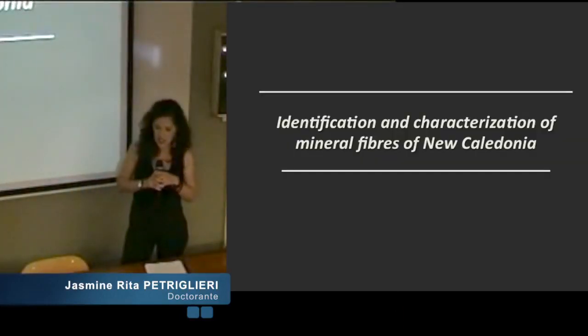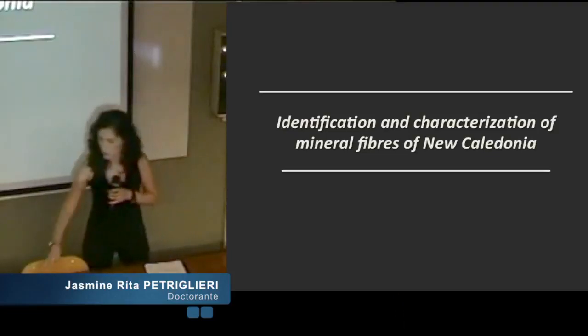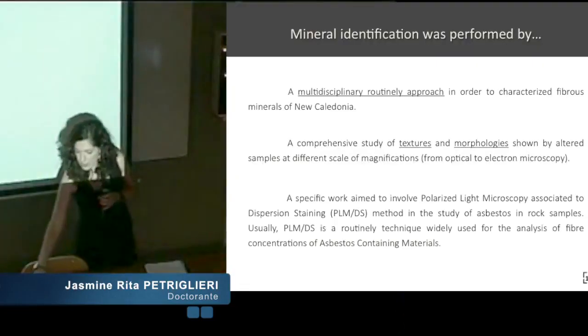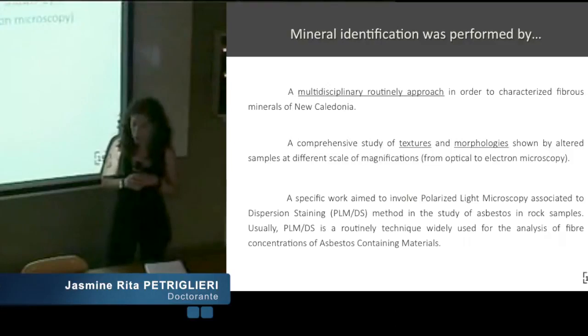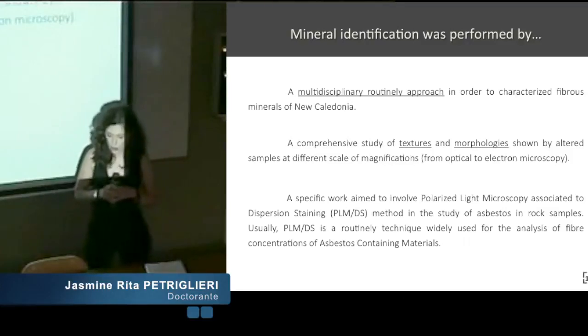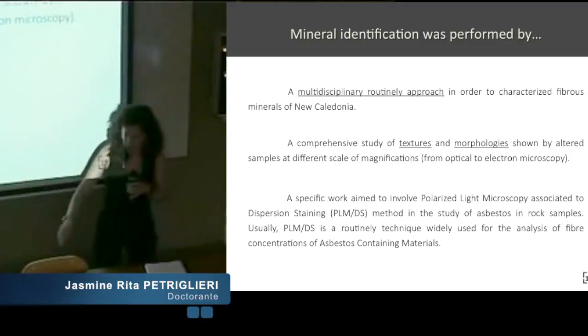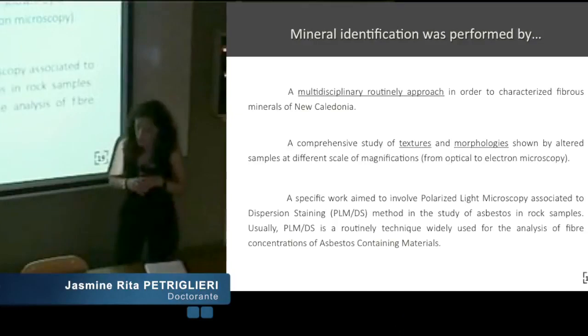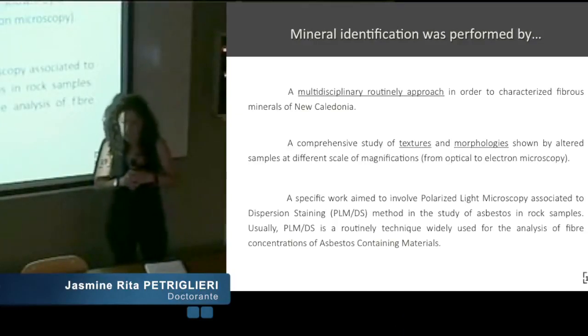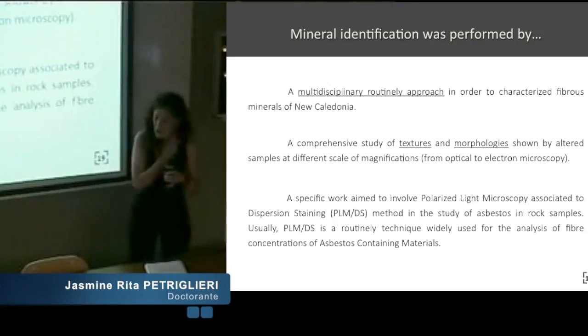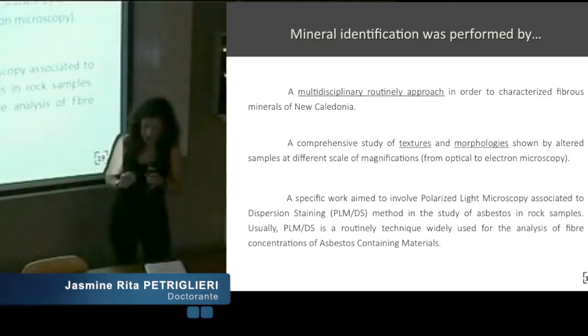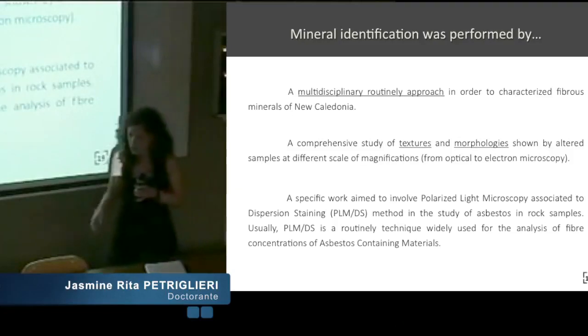Concerning the identification and characterization of mineral fibers of New Caledonia, mineral identification was performed by a multidisciplinary routine approach and by a comprehensive study of texture and morphologies at different degrees of alteration. In addition, polarized light microscopy associated with dispersion staining, a technique widely used for the analysis of fiber concentration in asbestos-containing materials, was applied to natural samples.